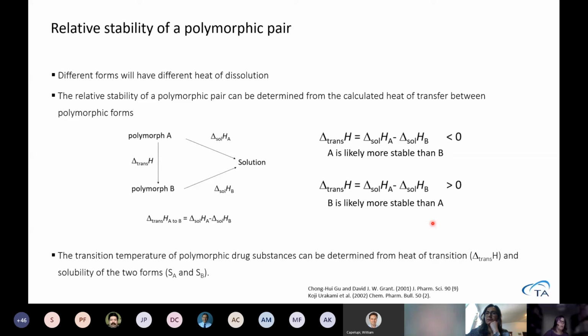Now I say likely because now we are only looking at the enthalpy, but as you're aware, the Gibbs free energy, whether it is less or more than 0, would actually determine the direction of the reaction. However, in the delta G you have enthalpy minus T delta S. But the entropy will be the same if your substance comes out in solution. So the entropy effect will be cancelled out here, so we can look at the enthalpy effect because it comes to the same final condition.